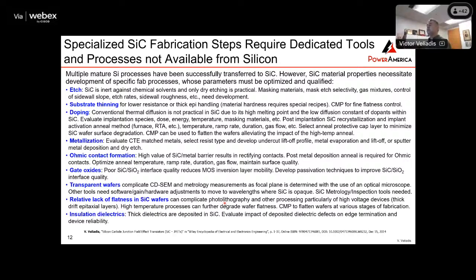And then finally, you have to deposit the dielectrics in silicon carbide, because you cannot have a thick thermal oxide, which, by the way, is part of what has made silicon very successful, that you can do a thick thermal oxide, and thermal oxides have very few defects. That's not the case in silicon carbide, so you've got to deposit insulation dielectrics.